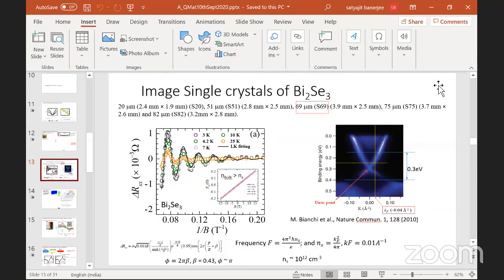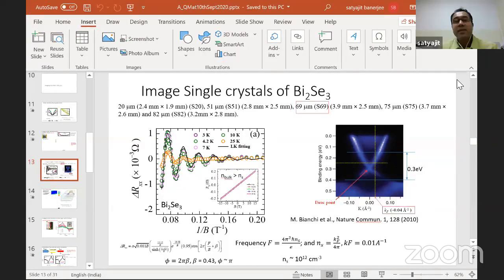Okay, so does that also mean that if I do these experiments, when you have the Griffiths phase, let's say a local probe experiment like STM, then I will see the Dirac point, the Dirac cone at certain points, but not at other points? I think at high temperatures, if you are able to do it at reasonably high temperatures, above 70 Kelvin in our crystals, it depends on what is the disorder concentration in your sample. But you should see localized regions where you will see this Dirac spectrum compared to other regions. Absolutely. Okay, thank you.